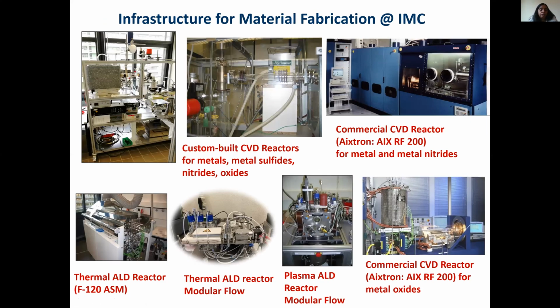So the infrastructure in terms of film deposition, you see that in the slide, we have some self-built CVD reactors where the students themselves assemble and they test the precursor. So the minute we have a precursor which is having good thermal properties, we test them in test reactors, and later on we transfer to the commercial systems that we have. This is for the nitrides, this is for the oxides, and this is all the CVD reactors, and these three beneath are the ALD reactors. It could be the thermal ALD, it could be the plasma ALD, and this is one of the small reactors we recently built. It's thermal, but basically for molecular layer deposition for organic coatings.